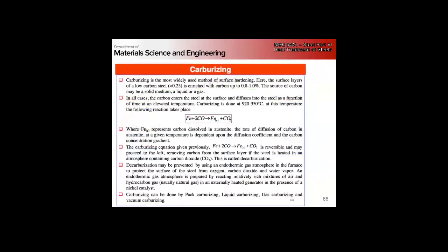You get oxide mill scale that forms, right? You probably saw this during the Jominy tests that you did, for the undergrads that are in the metals lab. So you get the mill scale that forms, and you've got a carbon depleted region at the surface. So basically, carburizing is we just put it in a carbon-enriched environment, and carbon, usually in the form of carbon monoxide, diffuses in, gives you iron with enriched carbon and carbon dioxide, right?